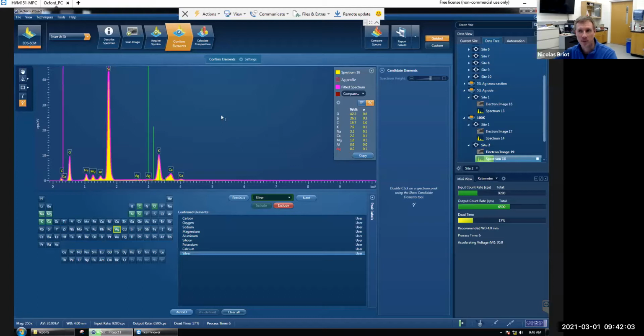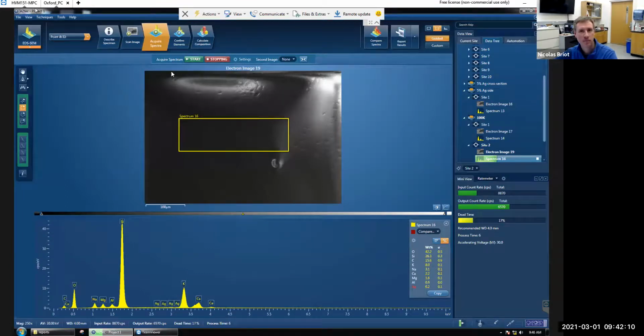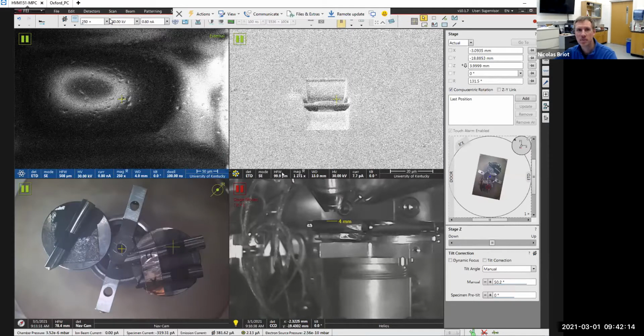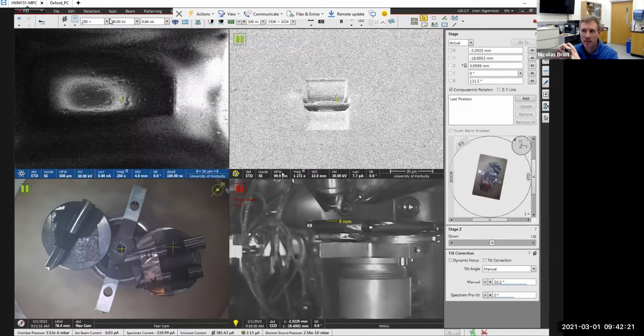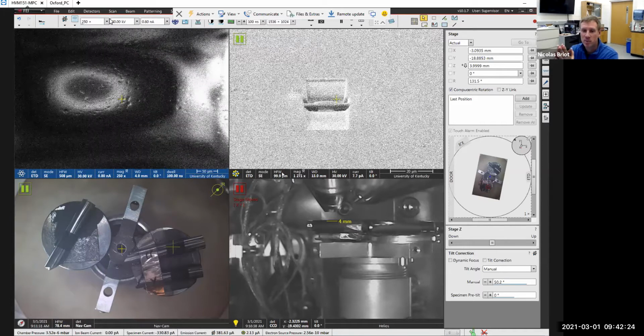I hope you're guessing what I'm doing. I bumped up the energy of the electrons that I'm sending to the sample, so they penetrate deeper. All of a sudden, the volume that we are analyzing is a little bigger, okay? And because the silver is mostly at the surface, as shown by the XPS, I want to see if the silver signal decreases in EDS. If it does decrease, and it did, that means the silver is really close to the surface. As you start probing deeper into the material, and I'm not talking tens of microns, I'm talking going from half a micron to a micron, you start to see the silver quantity decrease.